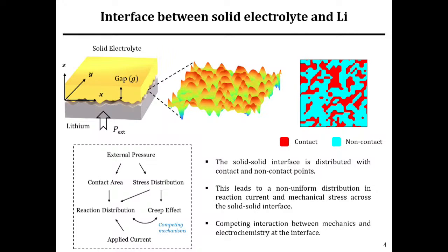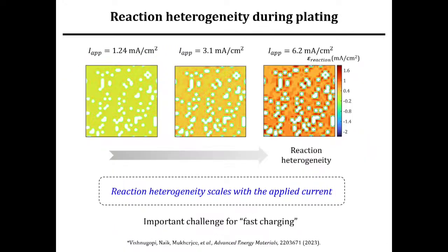These processes fundamentally alter the way in which lithium is electrochemically plated and stripped at these interfaces. Ideally, we would like to have a layer-by-layer growth of lithium and a layer-by-layer dissolution of lithium when you charge and discharge the battery. However, in most cases, the deposition morphology is quite heterogeneous, and this depends on various factors such as the microstructure of the solid electrolyte, the surface profile of the lithium, and also operating conditions.